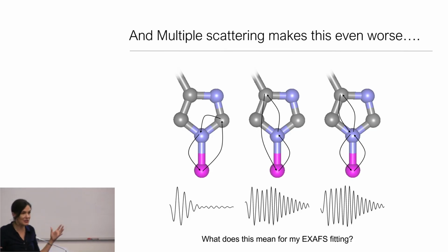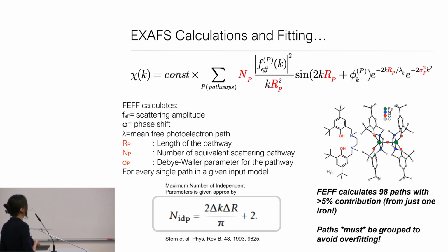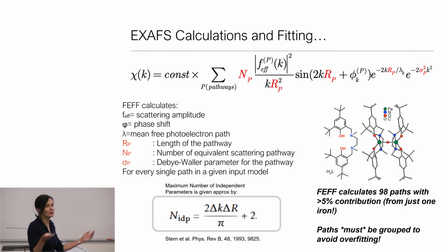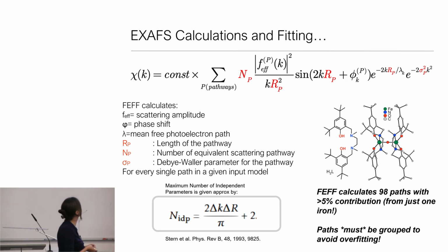We have so many possible paths that we can't possibly fit. So, for instance, if I take the same iron complex that I showed you the EXAFS for at the start, this is from Torsten Glaser's group, this iron-oxygen-iron complex, and I just put it into FEFF, it says there are 98 paths that have at least a 5% contribution. And I don't have 98 free parameters that I actually can fit, right?